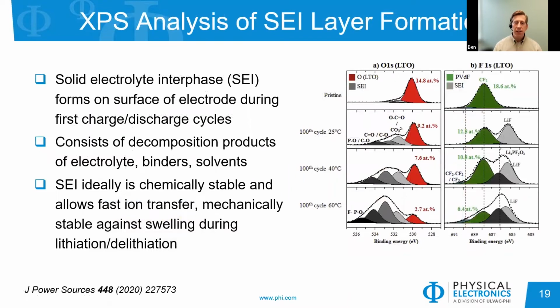Another area of interest is the SEI layer. The solid electrolyte interphase layer is what is formed when you put a somewhat pristine anode material combined with your electrolyte, your other materials, salts and whatnot that go together. And as you discharge and charge the cycle a few times, you will start to get some decomposition of those products and some reaction products forming on that surface. And in order to maintain good ion conductivity, that is an area that we would like to control. So there are certain phases, mechanical phases or grain sizes that you would like to achieve, certain reaction products that have good ionic conductivity.